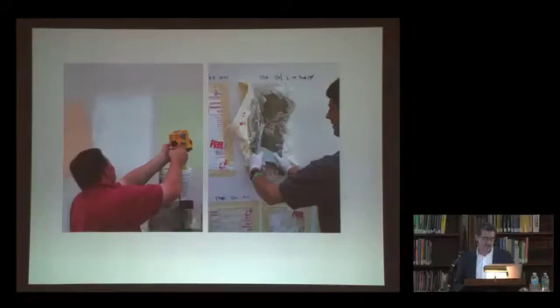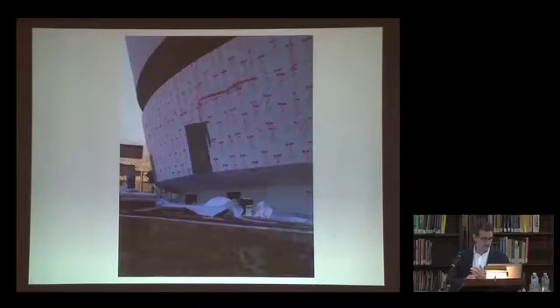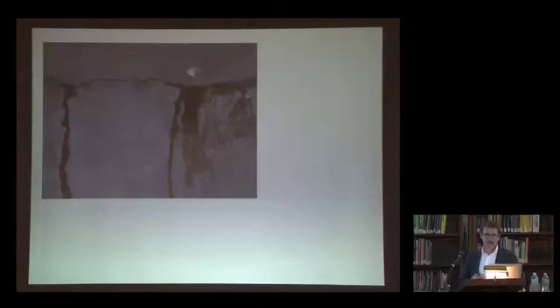So numerous products were tested to develop an effective way of removing the coating. And after we determined an appropriate procedure, full-scale removal was implemented. And the original concrete on all surfaces of the structure was now exposed for the first time since 1959. And this was done for numerous reasons. One, it had to be done to reapply a new coating in such a way that would have a long life. But also, the whole design team felt that we needed to see the surface in its entirety, to be able to compare and contrast the conditions, which enabled us to prioritize them